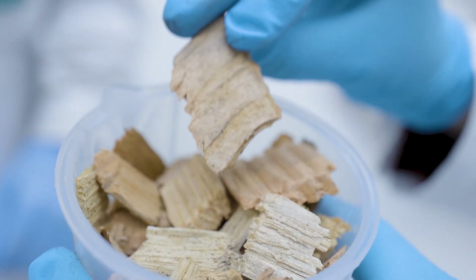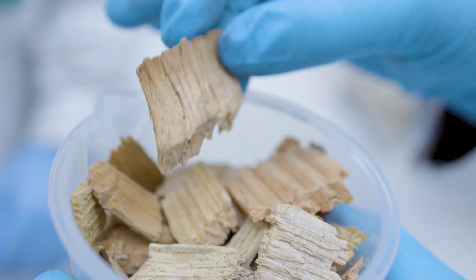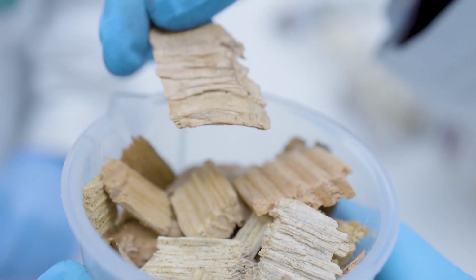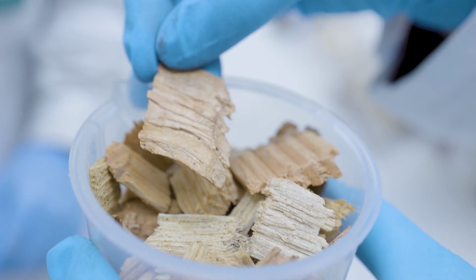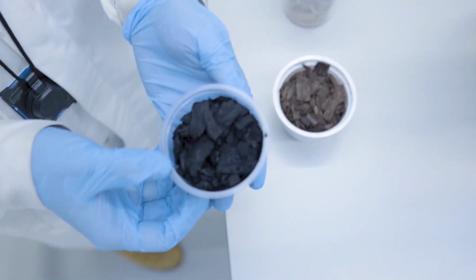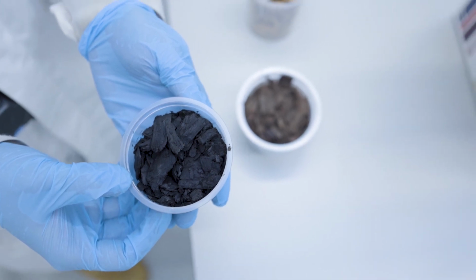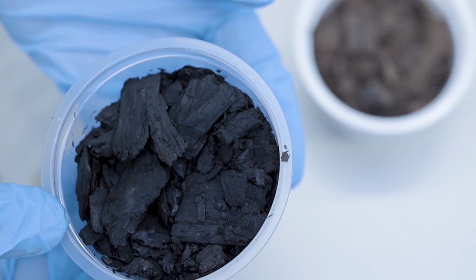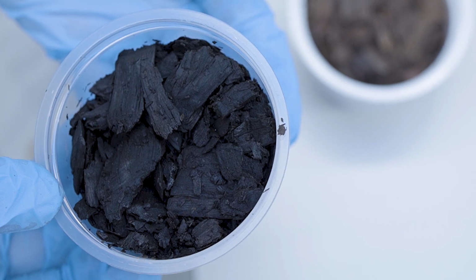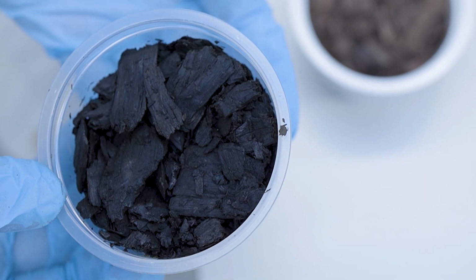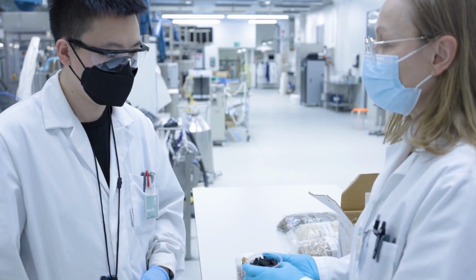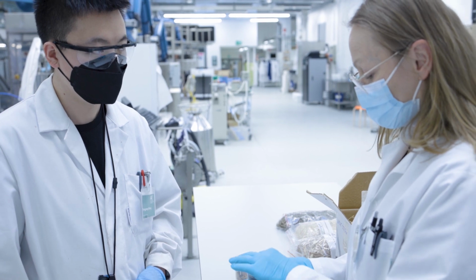In this Impress project, non-food agricultural and forest residual biomass is converted into industrial sugars and lignin by Avantium using Dawn technology, which is based on acid hydrolysis. After all the sugars have been taken out of the process, a high amount of residual lignin can be produced, typically 20 to 25% depending on the wood species.